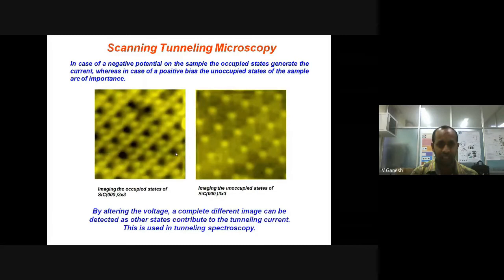Suppose you look at these two images. When you apply a negative potential to the sample substrate to induce this tunneling current, let's assume the occupied states, recall the energy levels I talked about on the sample substrate. If there are electrons present in the energy level, the occupied states would generate a tunneling current, and that will appear as a bright spot, and the unoccupied site will give a dark spot in the images. Now, if you reverse the polarity, the reverse imaging would happen, meaning the unoccupied site would give a bright image and the occupied site would become a dark image.